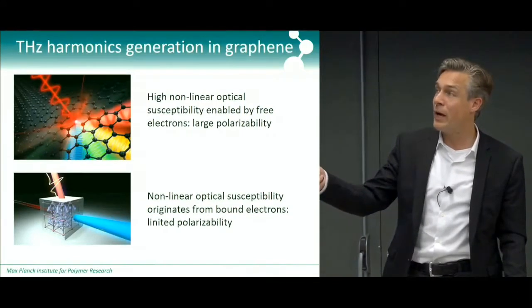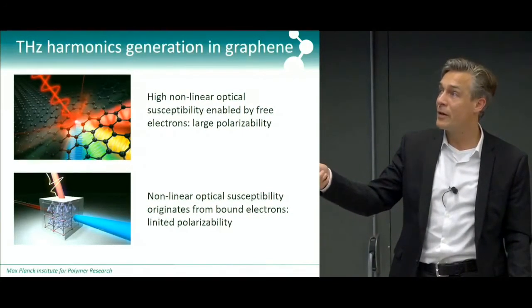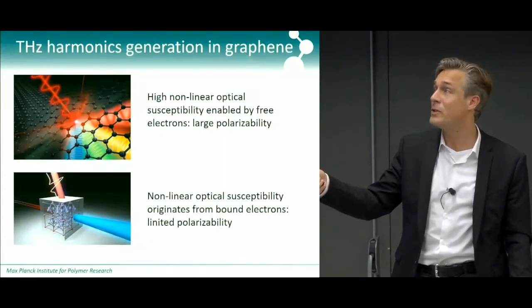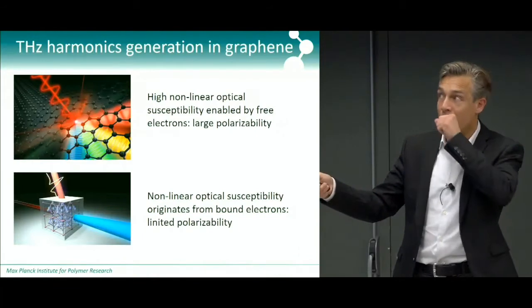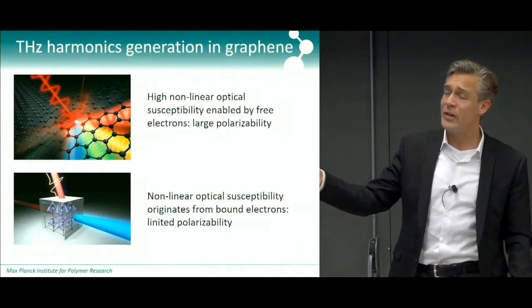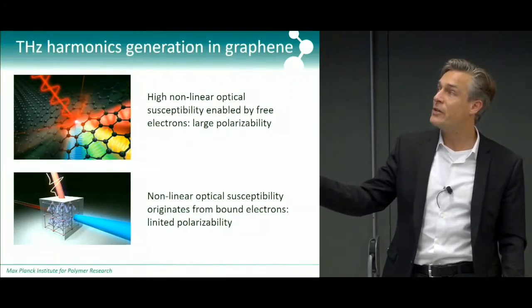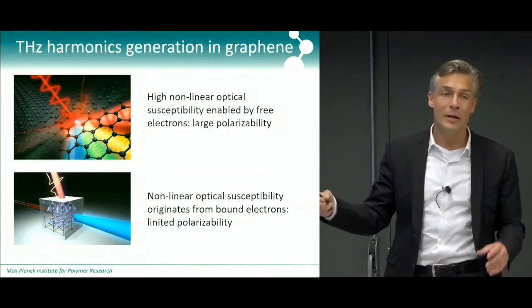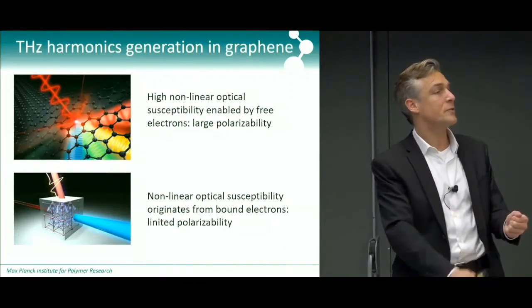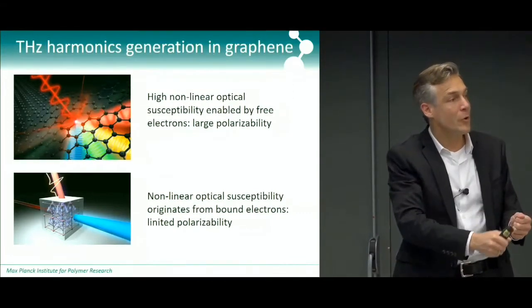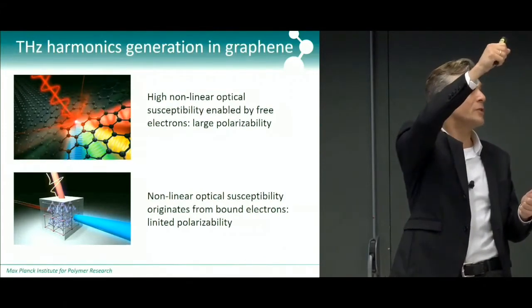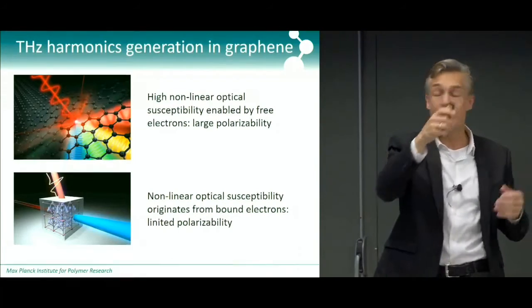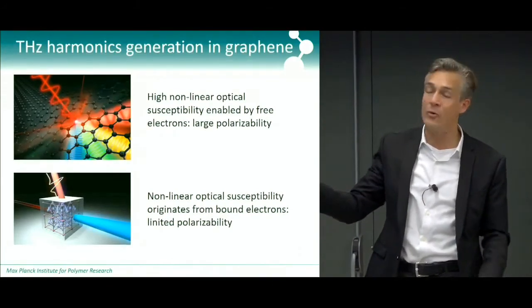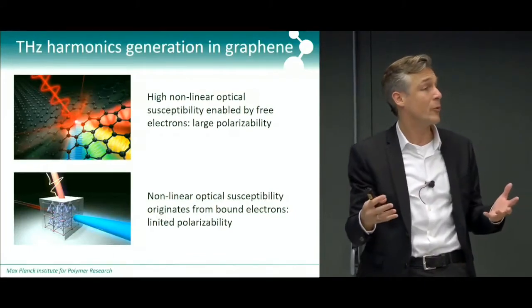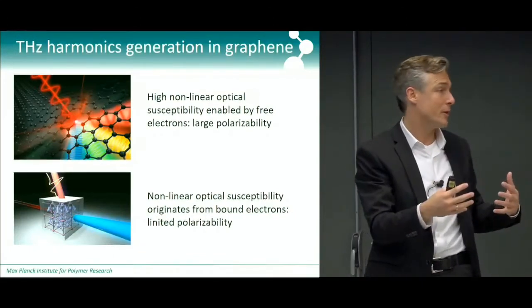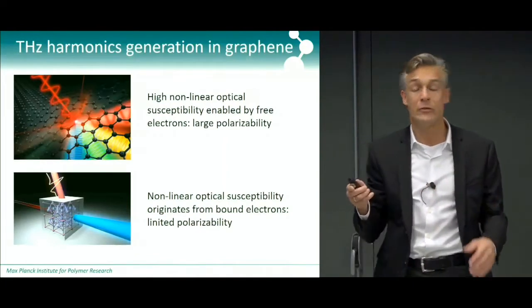So here I try to compare. This is a fancy picture of a terahertz pulse hitting the graphene and generating all these colors. And as I've told you, this is an extremely efficient process, and the reason for this high nonlinearity is that we have these free electrons. These free electrons can be accelerated, and they respond extremely nonlinearly to this acceleration in a collective way by heating up, and then cool. So they have a very large polarizability, because free electrons have a very large polarizability, and they have a very strong nonlinearity, which is exactly what you need for nonlinear optics.